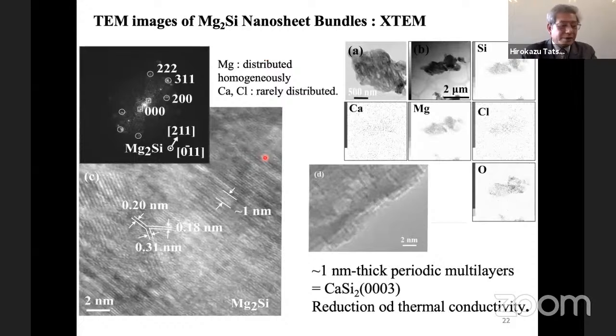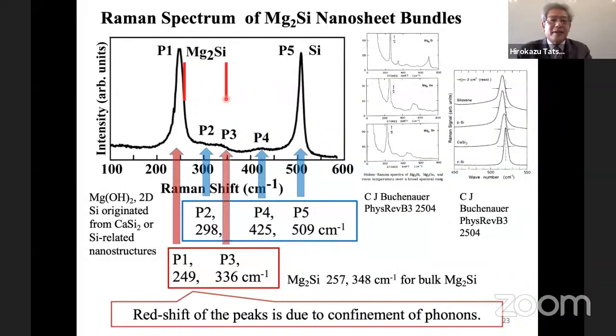So this is also a cross-sectional view. And for these materials, such a 1 nanometer periodic structure remains in the magnesium silicide. Magnesium silicide originally doesn't have such long-period structures. So this is the Raman spectra. This red line is the peak energies observed for the bulk case. This one is from the magnesium silicide nanosheet. Its peak is shifted and the tail is a little bit tailed. So it suggests the phonon structure is changed by forming the nanosheet structure compared with bulk materials.